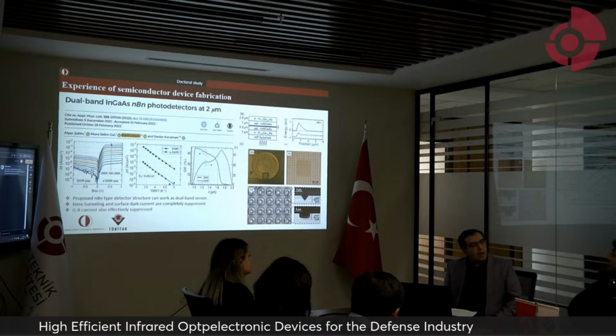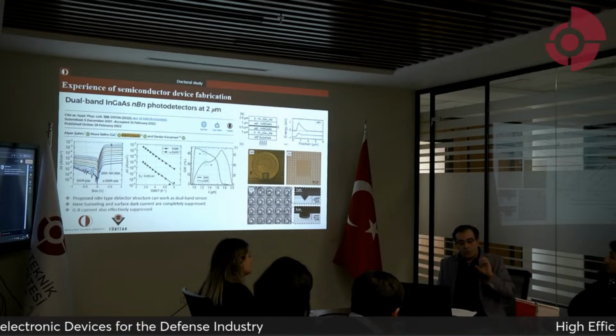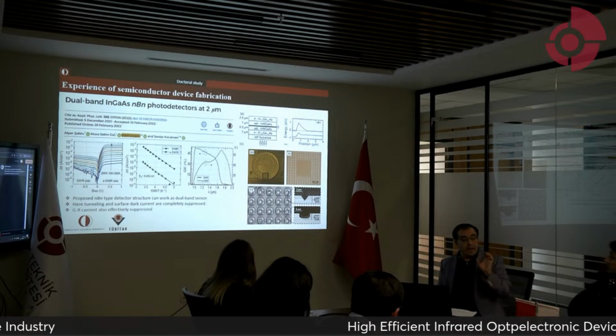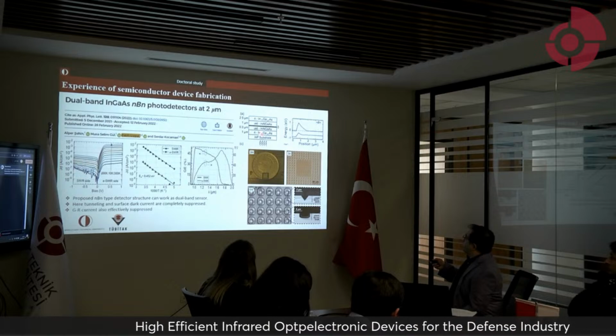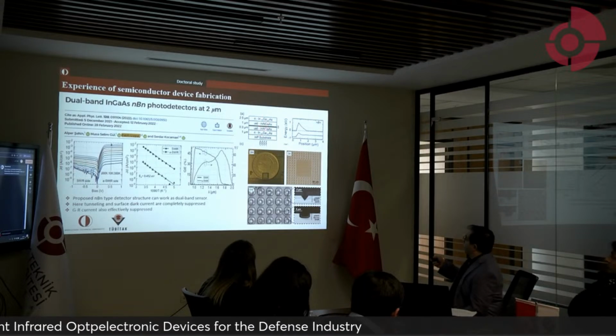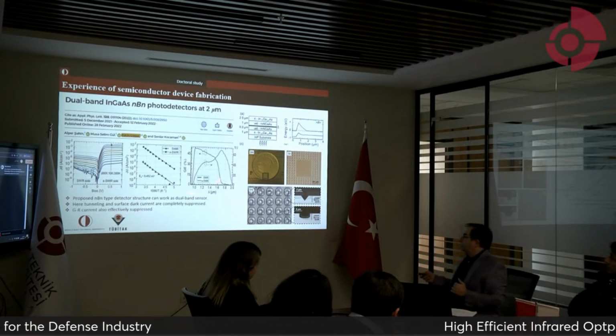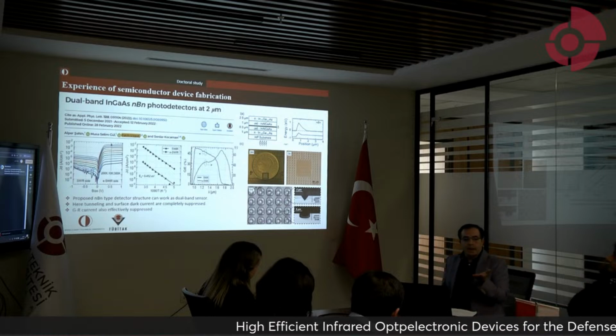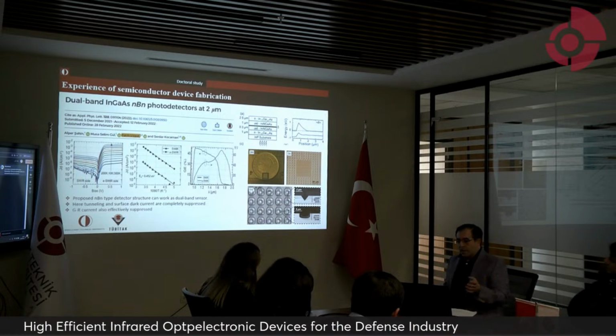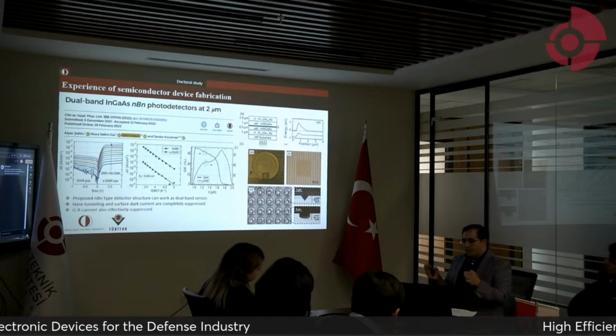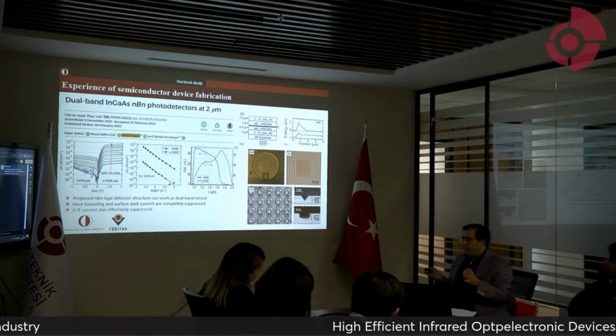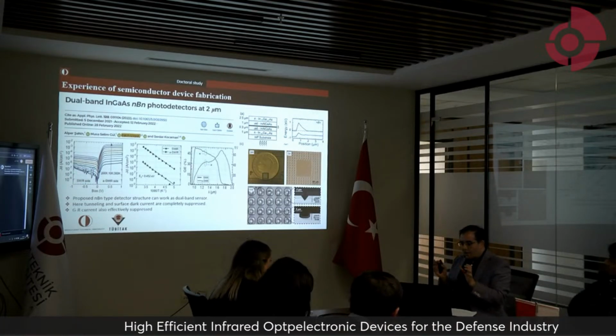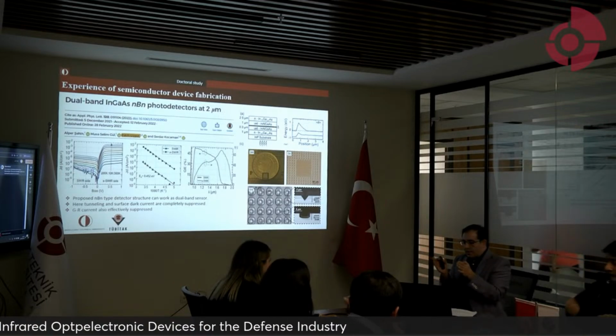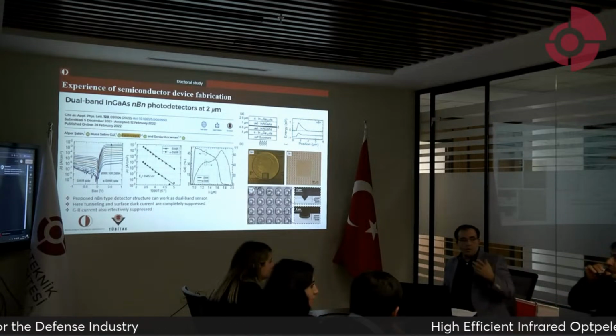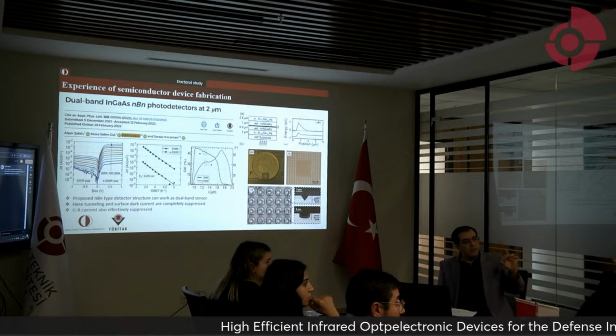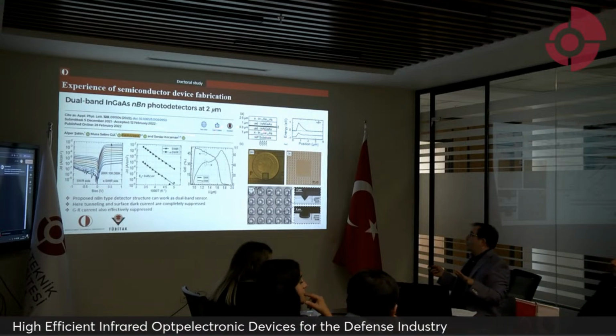Is there any limitation? Oh, yes, perfect. There is a limitation. It depends on the crystal dislocations and crystal defects. If you decrease the gallium, for example, you can go beyond. But indium phosphide is a kind of substrate. Think of it as a kind of building. You need to keep the same distance between these columns, and if you decrease or increase this mole fraction, the distance between columns gets smaller, the crystal structure gets worse, and the efficiency of the detector will be very low.